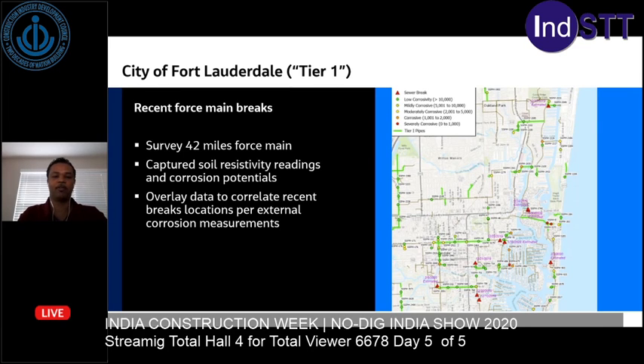So with tier 1, the city of Fort Lauderdale was experiencing a recent history of force main breaks. So we went in and performed a survey to see what was going on with the exterior surface of those force mains. We surveyed 42 miles of main. We captured soil resistivity readings and some pipe to soil potentials, and we used that data to overlay it with the recent breaks they had, and also to help identify any hotspot locations or any future locations with corrosion likelihood. Next slide.